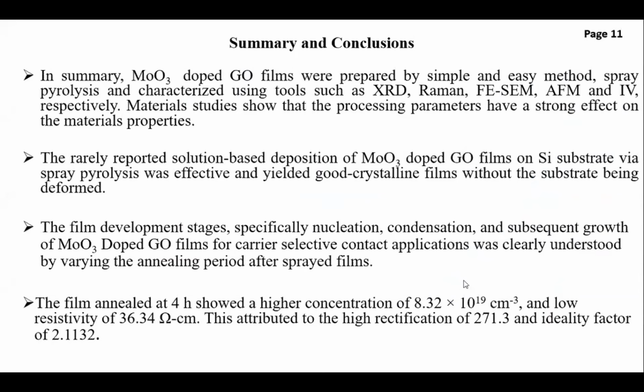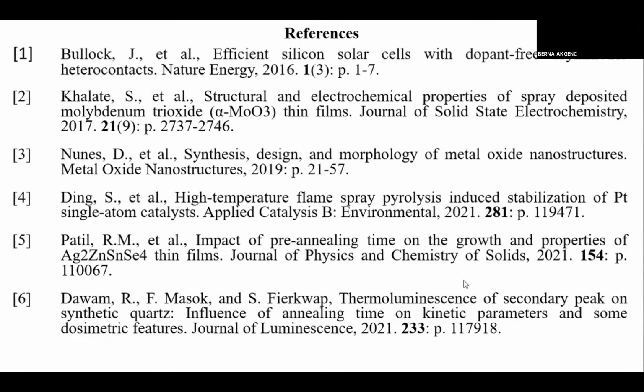The film's developmental stages, specifically nucleation, condensation, and the subsequent growth of molybdenum doped graphene for carrier selective contact application, were clearly understood by varying the annealing period after spraying the films. The films annealed at 4 hours showed a high concentration of 8.32 times 10 to the power of 19 per centimeter cube and a low resistivity of 36.34 ohm centimeter. This is attributed to the high rectification of 271.3 and ideality factor of 2.1132. These are some of our references.